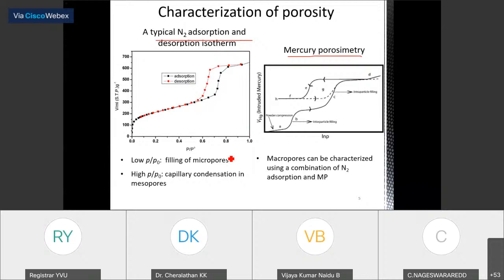So how to know a material is having micropores? You have to look at the lower P/P0 value. Okay. In this region, if you have a knee, a bend like this in the isotherm, then you can say that there are micropores. And if you have hysteresis or this kind of increase in the adsorption in the higher P/P0 value, then you can tell that it is having mesopores. So by this way, by using the nitrogen adsorption method, you can characterize these porous solids as microporous or mesoporous. Not only this, from this isotherm, we can also calculate pore size distribution. I didn't show the pore size distribution curves here, but it is possible.